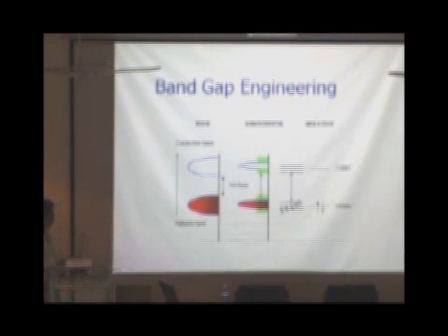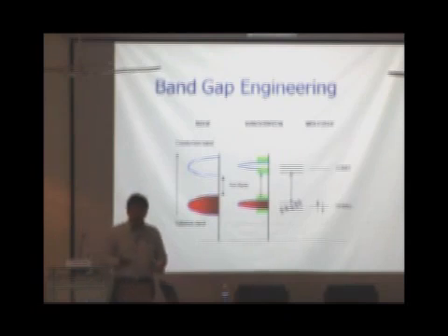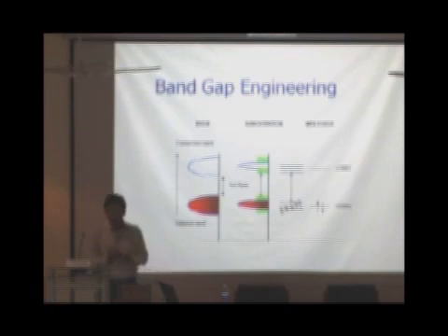But when you come to nanomaterials, when you start changing the size of these bulk materials and shrink it down, you come to a regime which is known as the quantum confined regime. In very simple words, what I can remind the students is that this is akin to a particle in a box like situation, where for a one-dimensional box you have n squared h squared by 8 m L squared, and you change the length of the box.